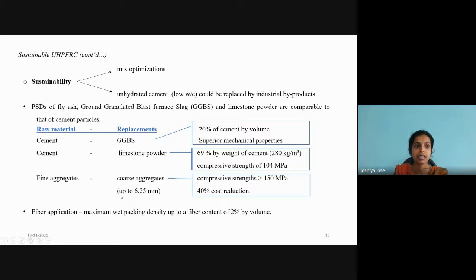And these are some of the case studies where the cement is being replaced with GGBS. Studies have found that about 20% of cement by volume could be replaced by GGBS. And limestone powder was also used to produce UHPC with ultra low cement content, around 280 kilogram per meter cube, still achieving a compressive strength of 104 megapascal. Even coarse aggregates were used to replace fine aggregates, and compressive strength greater than 150 megapascal with a 40% cost reduction was achieved. Also, efficient fiber application could be considered to attain a maximum wet packing density if the fiber content is about 2% by volume.